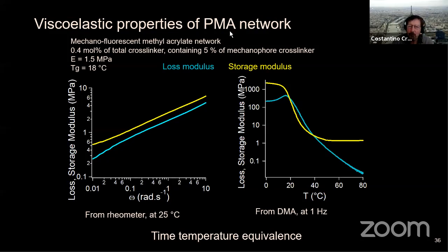So this PMA means methyl acrylate. This is a network that has a glass transition around 18 degrees C, so pretty close to room temperature, meaning that it's actually pretty viscoelastic at room temperature. And then as you increase the temperature, you go from 20 to 40 to 60, it becomes less